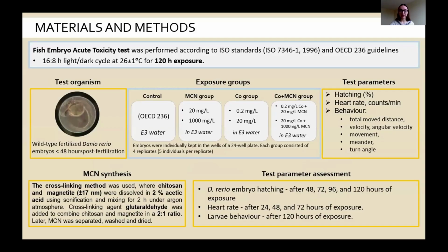And so yeah, we conducted the experiment on our model organism, zebrafish, Danio rerio embryos, and they were separated into several groups and exposed to different concentrations of contaminants. So this group was a control of water. Then we had the MCN group of lower and higher concentrations, so 20 and 1000 milligrams per liter of MCN respectively. The cobalt exposure group with a lower concentration of 0.2 and a higher concentration of 20 milligrams per liter, and also the cobalt plus MCN mixture group with lower concentrations of cobalt and MCN, and another one of higher concentrations of cobalt and MCN. And all these groups consisted of 4 replicates, where 5 individuals were observed per replicate.